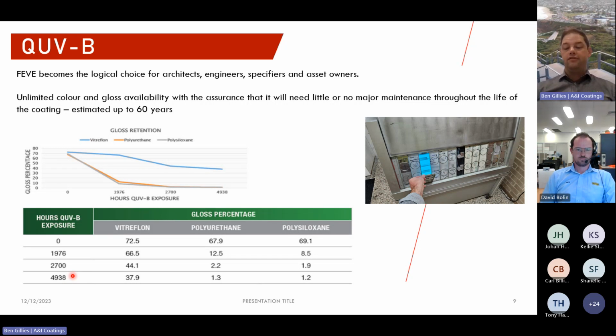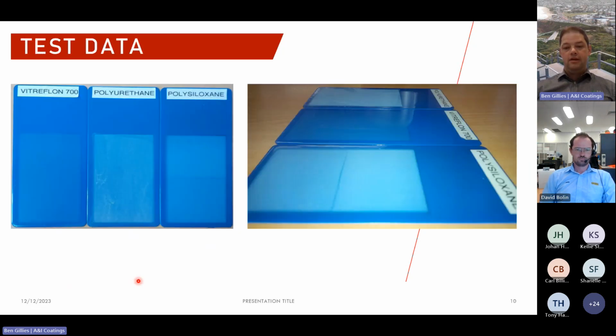And after nearly 5,000 hours exposure, which is equivalent to roughly 25 years real life, the fluoropolymer, Vitraflon is our brand name, the fluoropolymer has gone from 72 gloss units down to 37 gloss units. The polyurethane has gone from 67 to 1, and the polysiloxane from 69 to 1. So right now, these would be looking very tired, ready for a repaint. And what we'll see on the next slide, what this actually looks like.